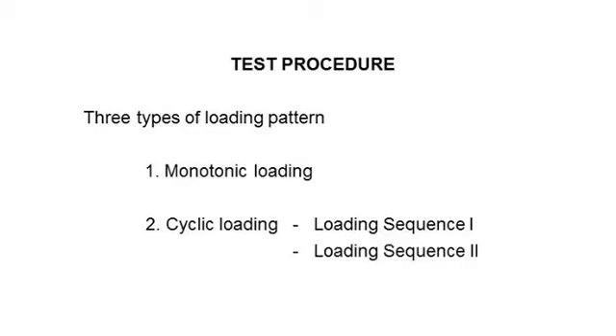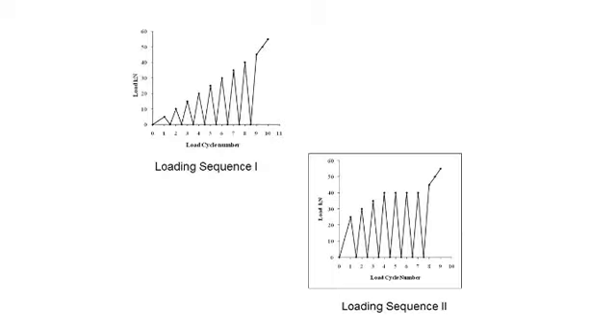So 2 different loading patterns were followed: monotonic loading and cyclic loading. Under cyclic loading, these are the 2 different loading sequences adopted. The loads were gradually increased till ultimate, and in the second loading sequence, close to the ultimate, the number of cycles were repeated, and then it was taken to the ultimate load.